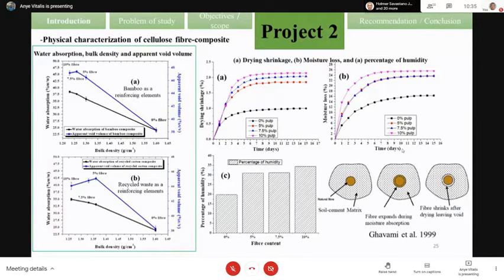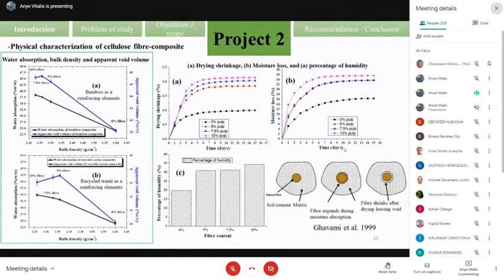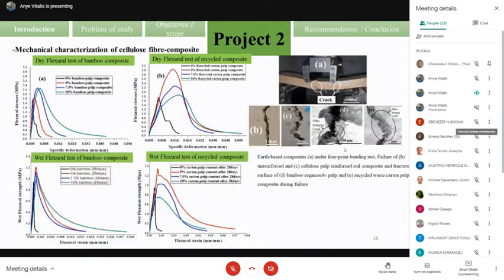This is due to the fact that during the mixing of our fiber with the matrix, the fiber, with a high capacity of absorption, absorbs water and swells. Now when it dries, it comes back to the normal dimension, and it releases pores between fiber and matrix. That pore will be used as a water reservoir to absorb moisture. That's why we are increasing the moisture during the drying process.